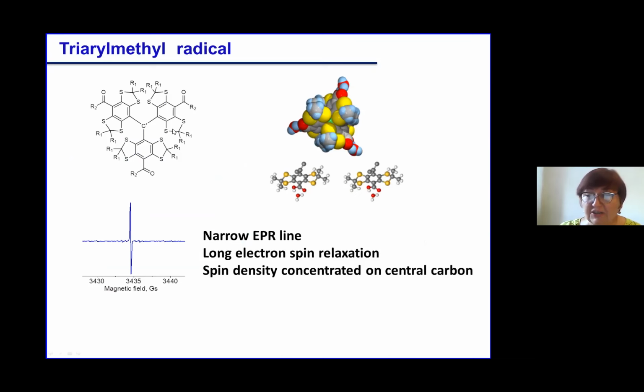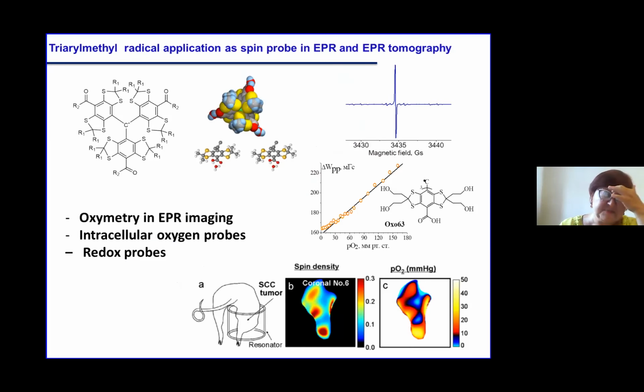So what is a triarylmethyl radical? It has such a structure, and the main peculiarity of this radical is a very narrow line in EPR. That means very long electron spin relaxation. Spin density is concentrated on the central carbon and is very much shielded. And because of that, it has very high stability in many media. So for many years, this radical was used in oximetry to measure oxygen. Why is it so? We can make a calibration in model conditions,